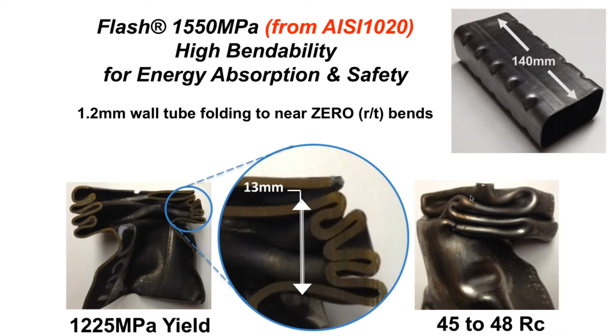Those aren't perfect zero T bends, but they're pretty darn close. In a recent study by U.S. Steel, they found that the ability to bend is almost synonymous with the ability to absorb energy. It's a very good indicator. So we've got a very bendable material, and we also know that energy absorption is very good.